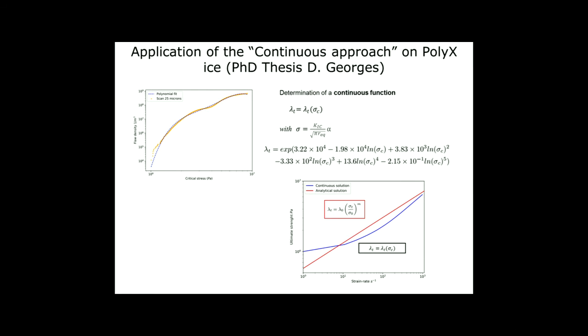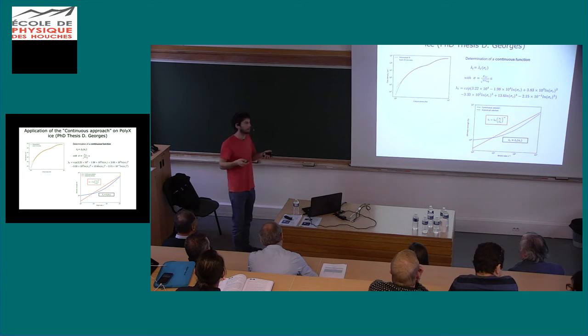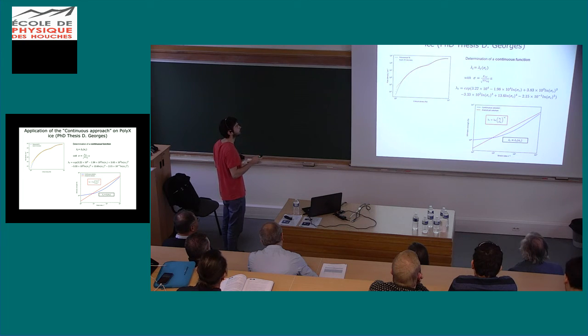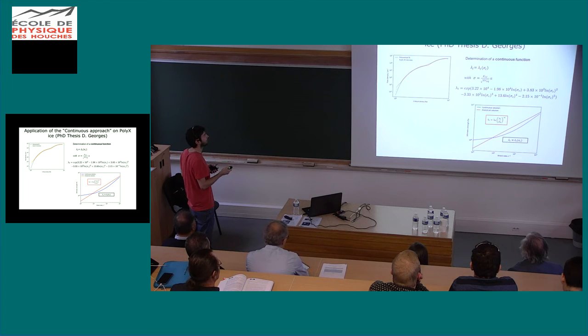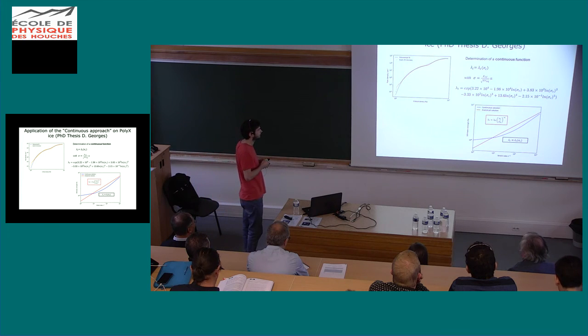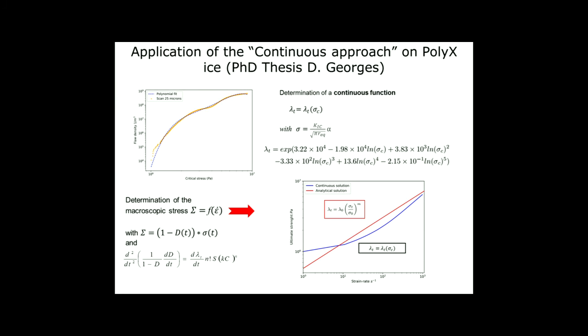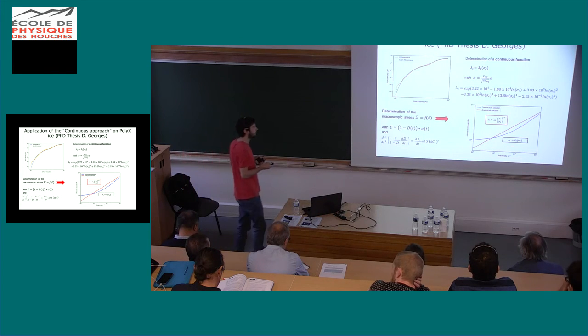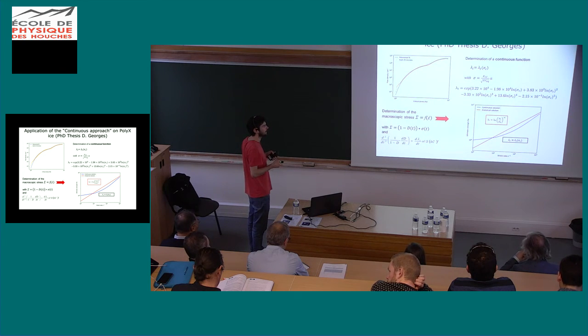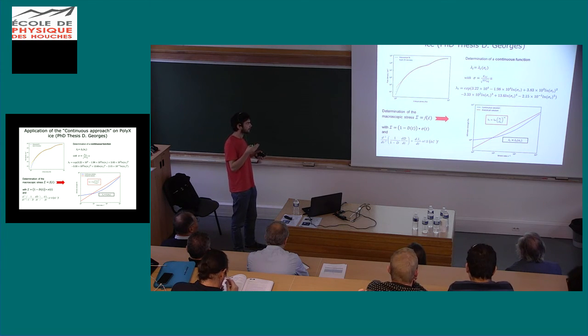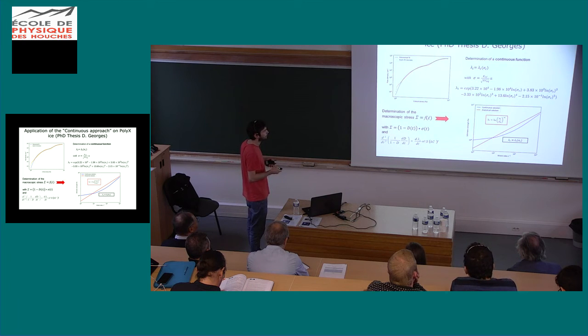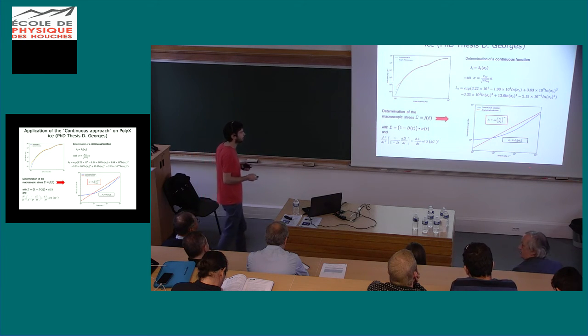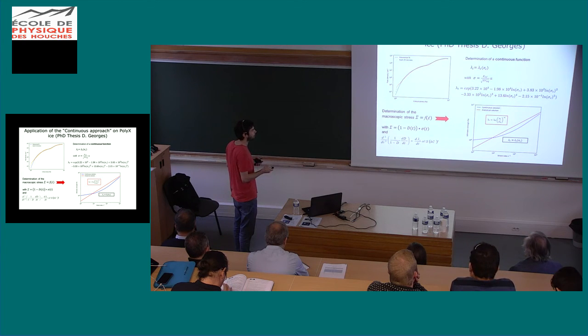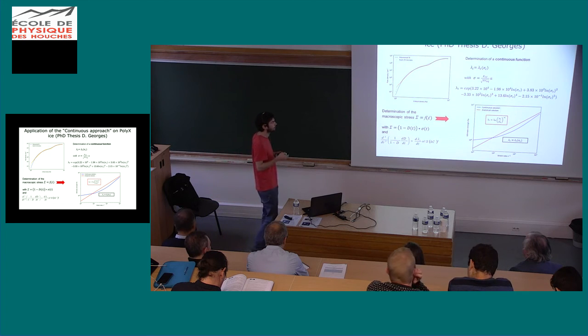So from this flaw density distribution, it's possible to determine a continuous function fitting our bubble distribution, to determine a critical flaw density as a function of critical stress. And here you have a graph with the different solutions. In red, you have the analytical solution that takes as input parameter the critical flaw density following the Weibull law. And in blue, you have a continuous solution, taking this critical flaw density. Here you have the ultimate strength as a function of the strain rate. You can see that the shape of the continuous solution reproduces the original bubble size distribution in a better way.